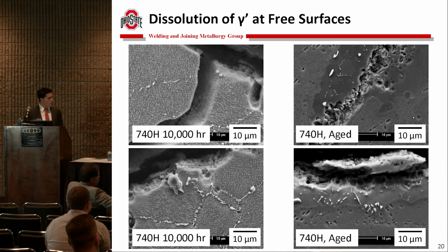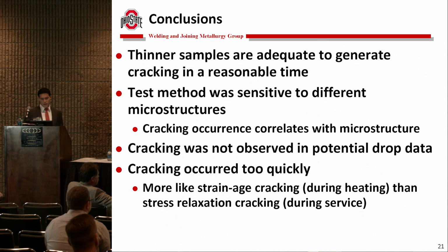So the so what from this, my big conclusion, is that it worked. The thinner sample worked, which is really what I set out to figure out in round one. And so not only did cracking occur, but the test method was sensitive to different microstructures. And so, as I tried to step through with you, the grain size and the precipitate presence were clearly the controlling factors.